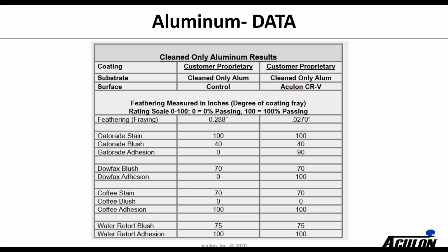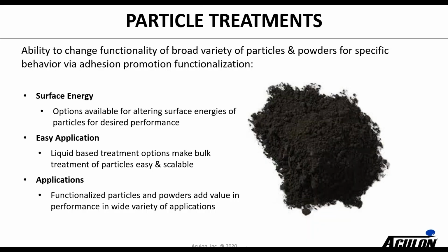So here's some additional data that shows when you start stressing the treatment with Gatorade, Dowfax, coffee, you see a nice improvement pretty much across the board. In some cases it's just equivalent, but in other cases you see a pretty nice improvement by using the Aculon primer.